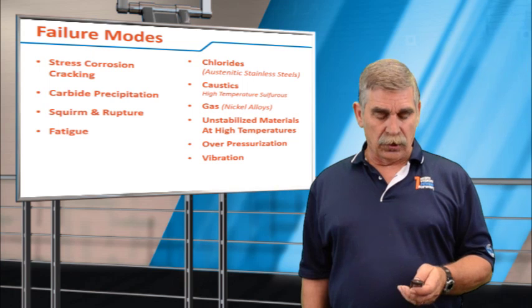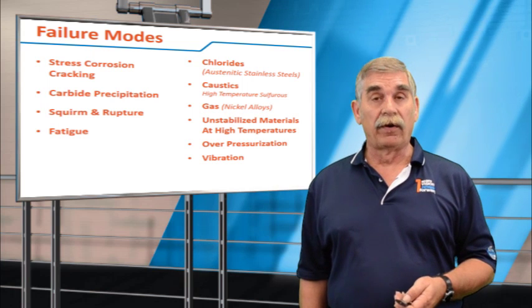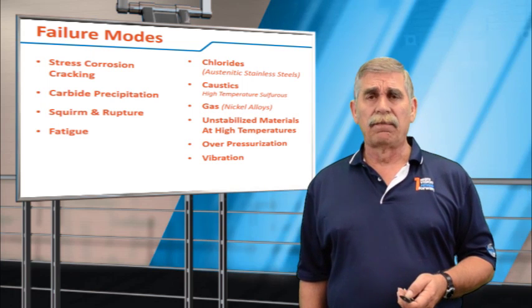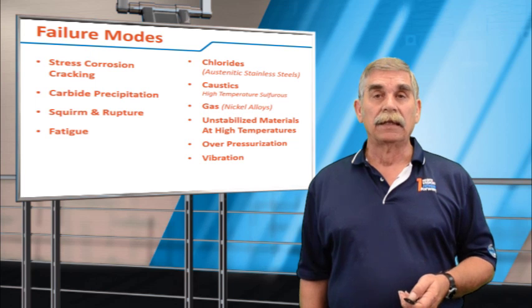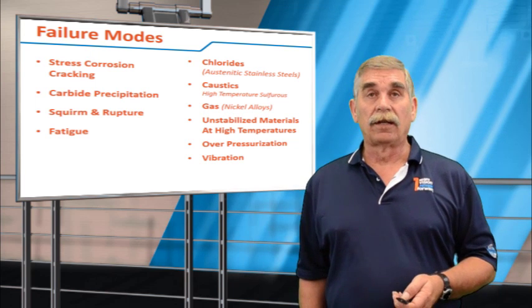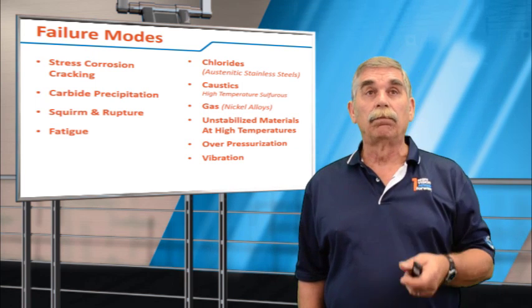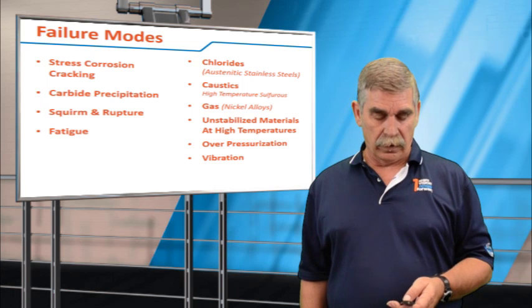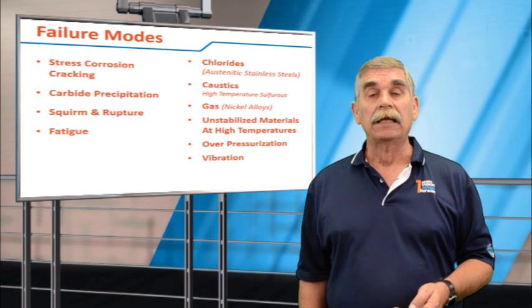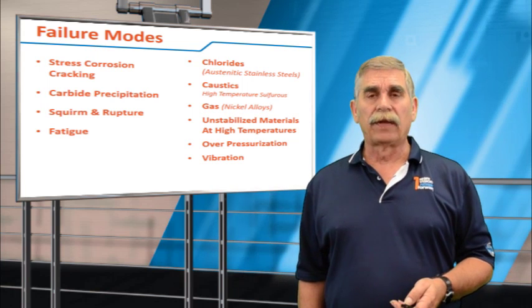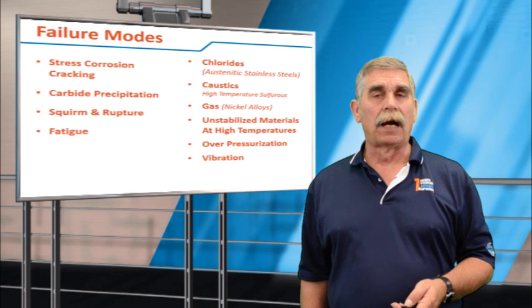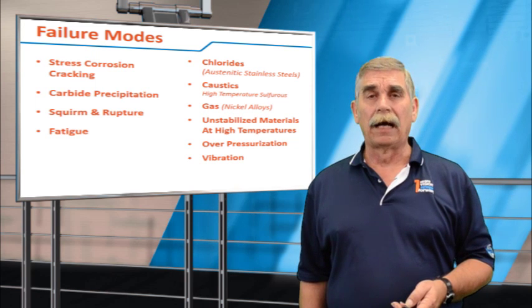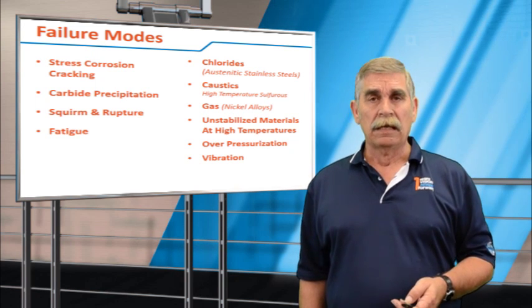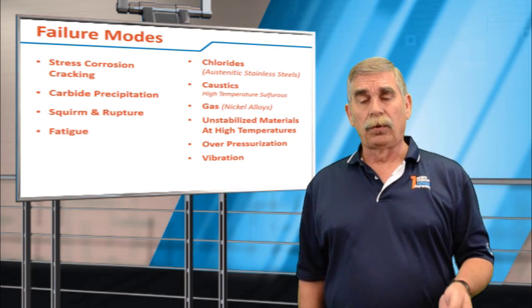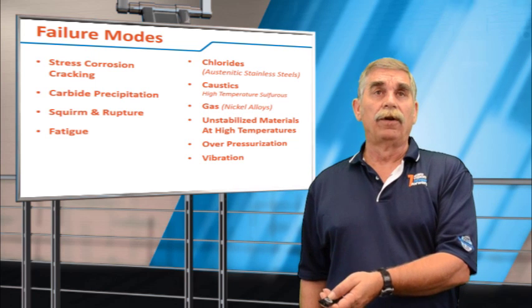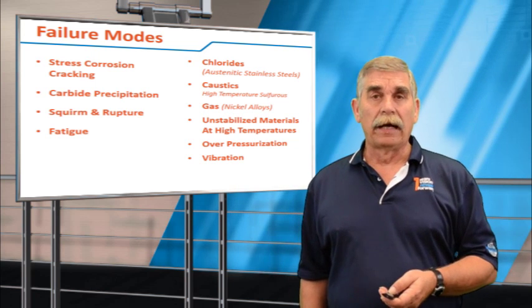Carbide precipitation is something that happens at very high temperatures, say above about 950 degrees. That will occur in your austenitic stainless steels. We do have an embrittlement phase for the high nickel materials that also operates in the creep range. And so for that reason, we generally like to see the bellows operating temperature below about 950 to 900 degrees. So if you can get your bellows operating between 400 and 900 degrees, there's no reason why it shouldn't last